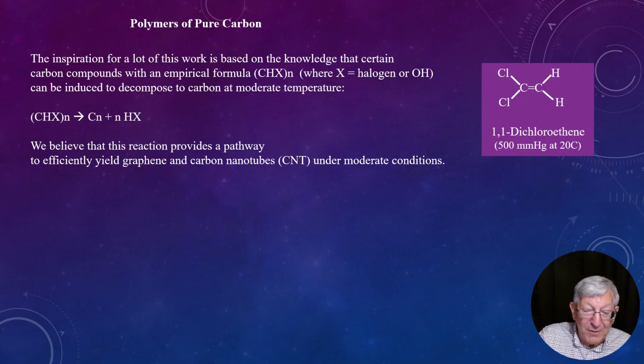Anyway, this thing forms a polymer very readily. And Dow Chemical Company was doing this research, and they discovered that you can make this polymer very easily, what they call polyvinylidene dichloride, PVDC, I guess is the name they called it. And the polymer has interesting properties in that it resists the penetration of oxygen. So the idea is we'll make fibers or film, and we'll use that to create an oxygen barrier, which is very good if you're wrapping up your sandwich. You want a sandwich that's wrapped up in this stuff, and oxygen can't get to it, and the sandwich will stay fresh for a long time.